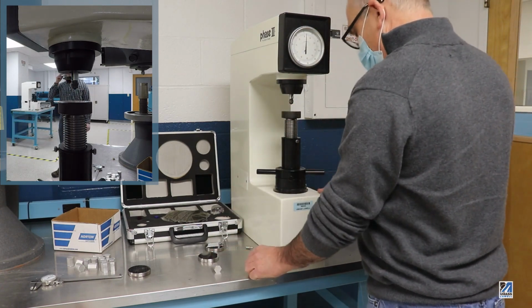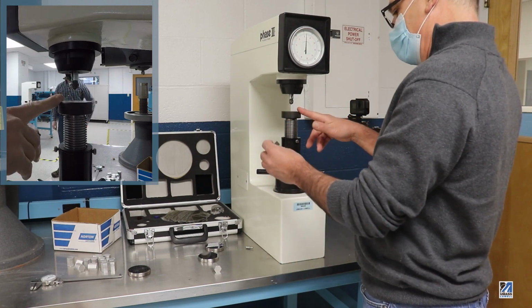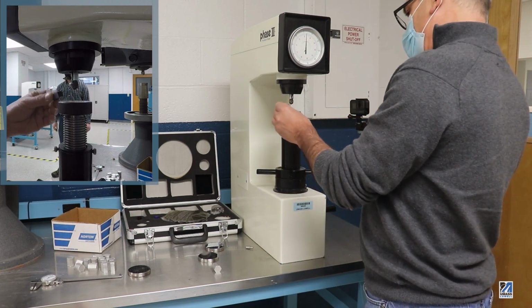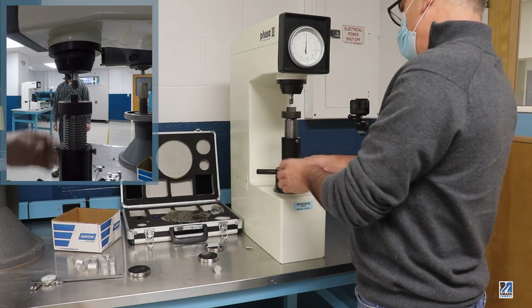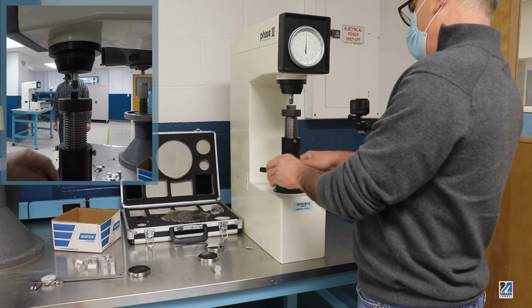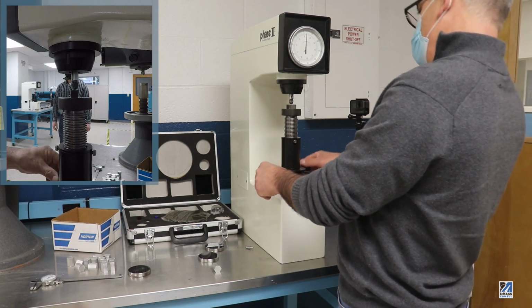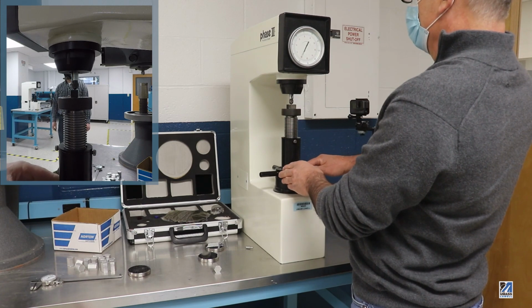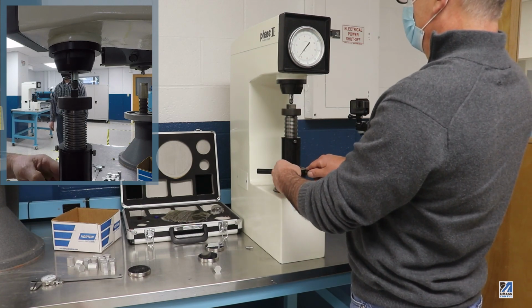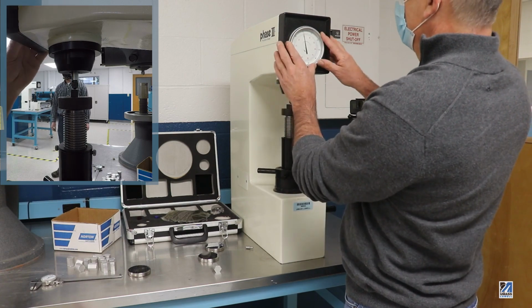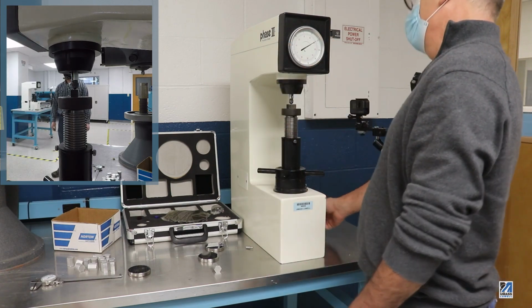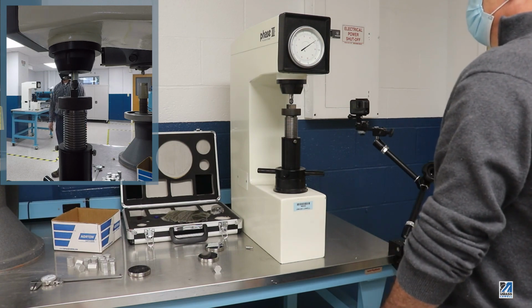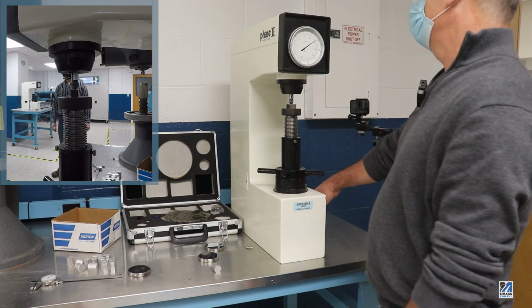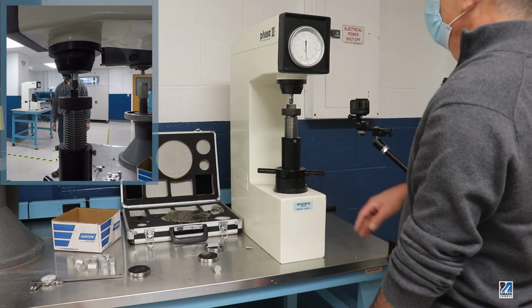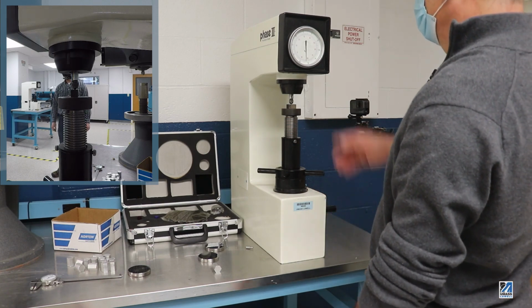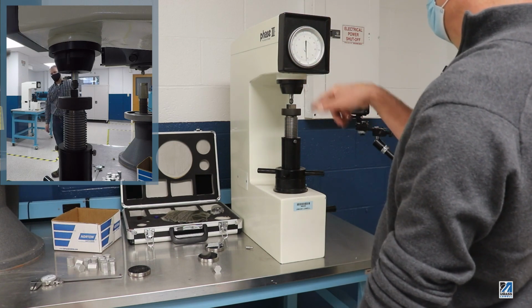Okay, while I have the Rockwell B set up on the hardness tester, I have my oil quenched sample. That was the 1018 that we heat treated already for approximately 30 minutes at 850 some odd degrees. Same thing, what I want to do is go ahead and apply minor load. Applying the major load. Wait for it to stabilize, and then remove the major load. And this appears to be a Rockwell B of approximately, where am I at? 82.